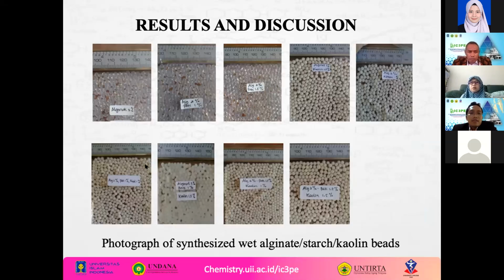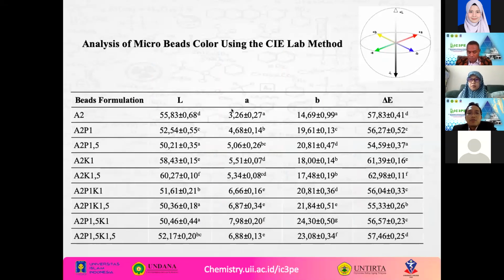The addition of starch did not change the color of the beads, but the addition of kaolin changed the color from transparent to white and yellowish. This is alginate, this is alginate and starch, this is alginate and kaolin, and this is alginate, starch, and kaolin. And this is the microbead color using the CIELAB method. L is the darkness value, a is the reddish value, and b is the yellowish value. The color based on CIELAB changed significantly because of the addition of starch and kaolin.